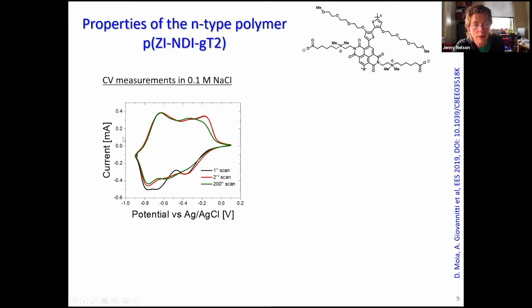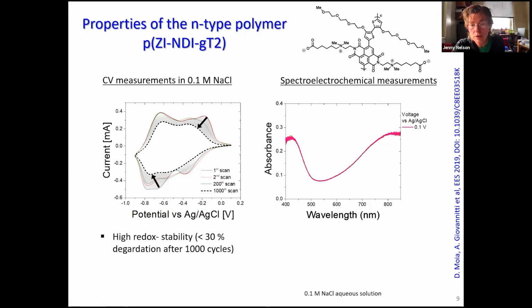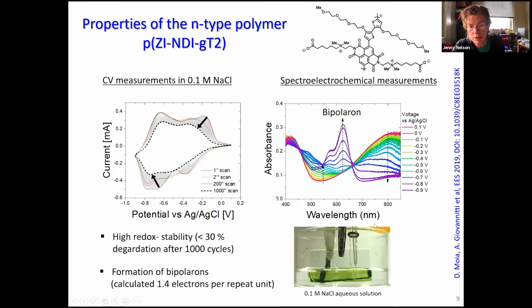Similarly, with the n-type polymer, we saw reasonably reproducible CV performance, with some loss after thousands of scans. And again, we see very nice changes in color as the material is cycled through to the polaron and then to the bipolaron state. In this case, both the polaron and the bipolaron have signatures in the visible part of the spectrum, so when you cycle the polymer, you actually see the color change twice. It goes from green to brown to gray and back again as it goes through the polaron and the bipolaron. In the case of the NDI-T2, the bipolaron signature is very characteristic and very easy to recognize. That's something we're going to be using as a tool later on to study the stability of polymers.